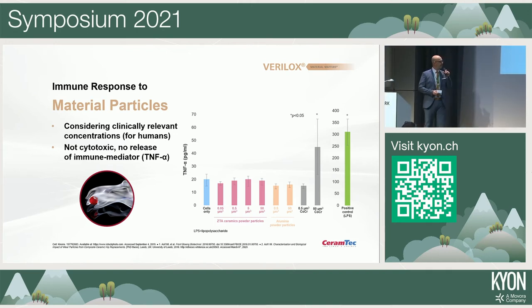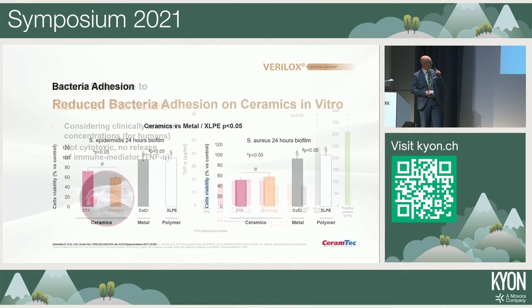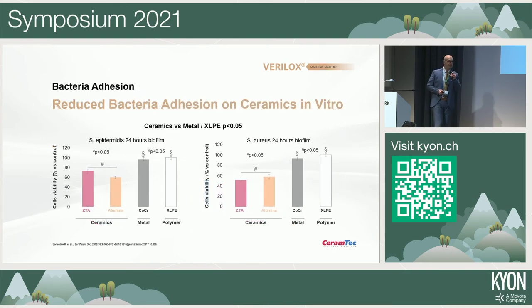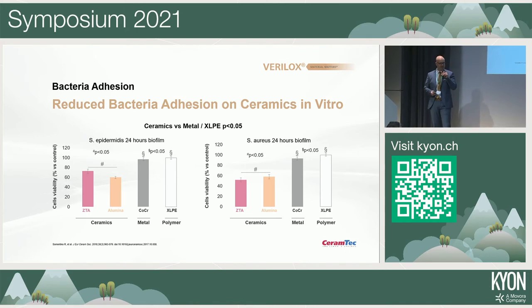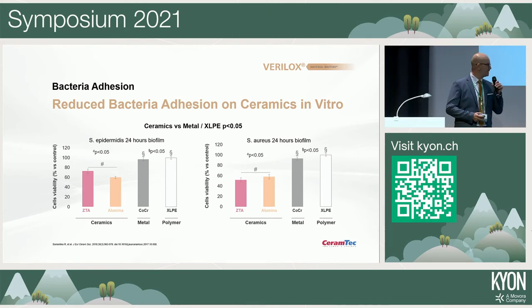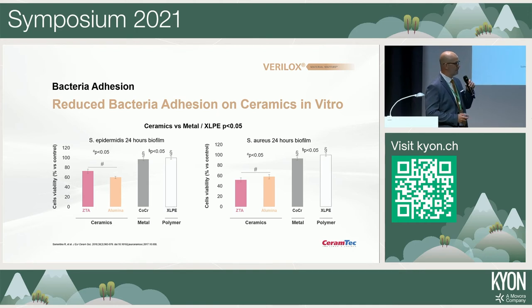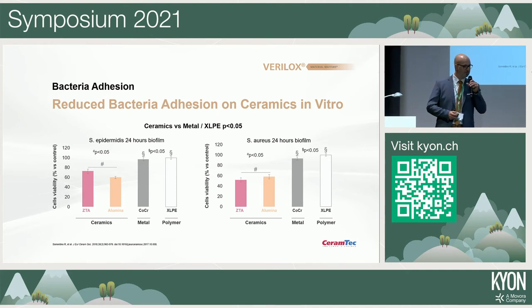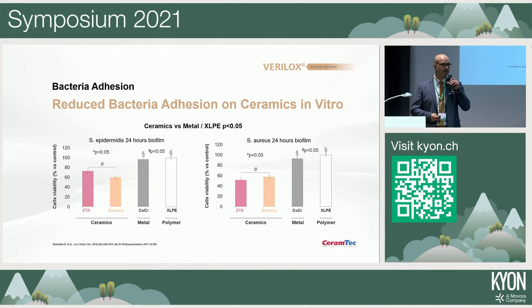And the last topic which I want to point your interest to here is the adhesion of bacteria. Infection was mentioned today, so it's also an issue in veterinary application. And with ceramics, in the studies, we found that you have less adhesion of bacteria on the surface. So if you compare ceramics with other materials used in implantation like metals and polymer, you see that even after 24 hours, you have a lower amount of bacteria on top of the surface than with the other materials which we compared it to.